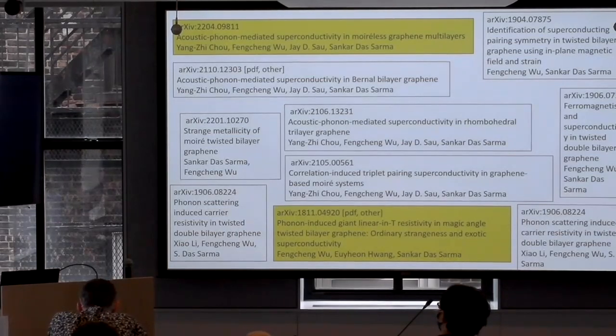Second, many experiments do not see linear down to very low temperature. People just quote the ones which do. I have looked at 500 resistivity papers. In some, it doesn't go to very low temperature. In some, it does. It's definitely not universal. What is universal is that there is a regime where it's linear. And the electron-phonon coupling that you need, if you do a back of the envelope calculation, is strong coupling, the age of strong coupling superconductivity. You need something like 1.5 to get the correct resistivity.